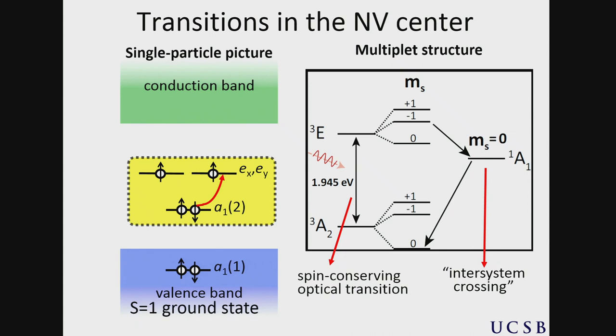And then these levels in the particular symmetry of the NV center are A1 levels and E levels. They are occupied with electrons in this way. In the particular charge state that you want for this center, which is actually a negative charge state, you have an S equal one ground state. And then by exciting an electron optically out of this A1 level to an E level, you can actually get it into an excited state, as is illustrated on the right-hand side here. And the energy of that optical transition is 1.945 eV. And, of course, then you get also luminescence around that energy.